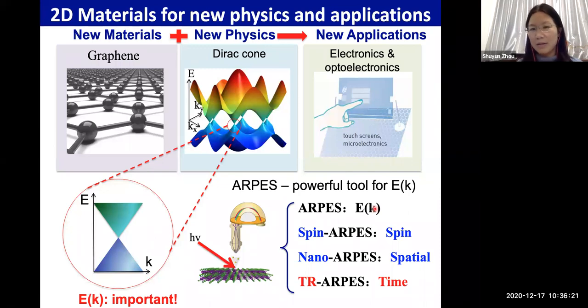In recent years, there has been major progress in spin-resolved and also nano-resolved ARPES. In particular, for 2D materials, which are small in sample size, for example, an exfoliated flake, nano-ARPES is very important for this kind of electronic structure study. In addition, in my group, we have invested a lot of time in developing time- and angle-resolved photoemission spectroscopy. This allows us to probe not only the energy and momentum resolved information, but also the dynamics information.